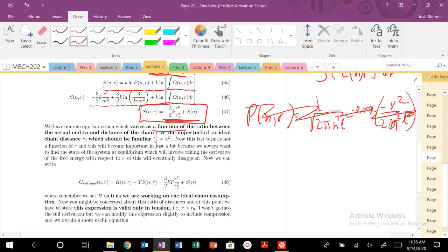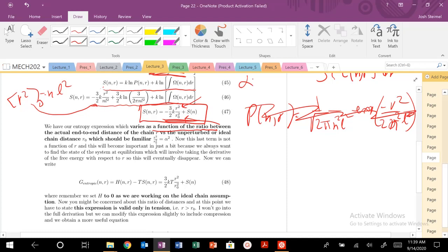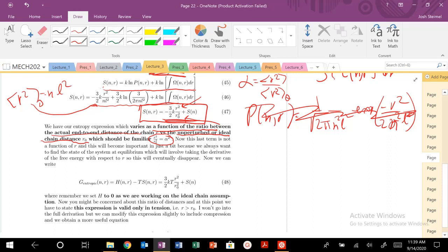Entropy varies as a function of the ratio between the actual end-to-end distance R and R-naught, which is the ideal chain end-to-end distance: for an ideal chain, R² = Nl². That's R-naught squared. The actual R² is your real end-to-end distance — just like our alpha definition, which was R²/R-naught². We're just taking out the averages here; R-naught is the unperturbed or ideal chain distance in a theta solvent, and R is the actual end-to-end distance in whatever solvent or condition.